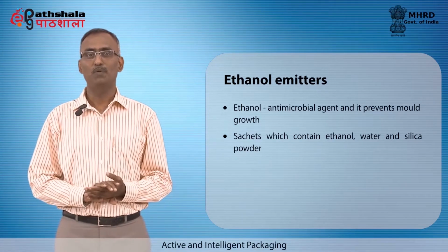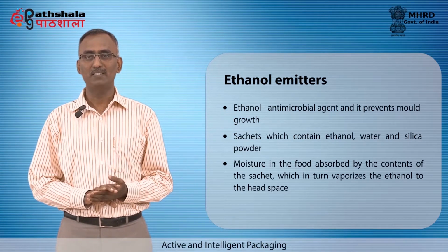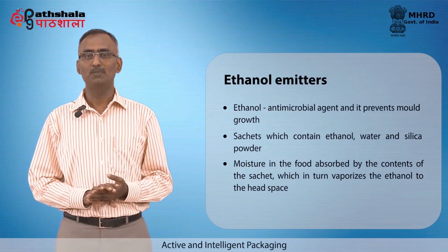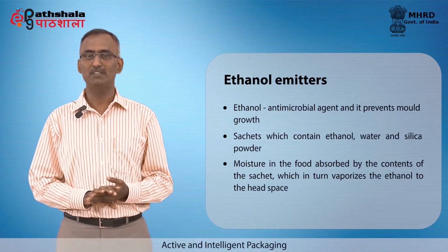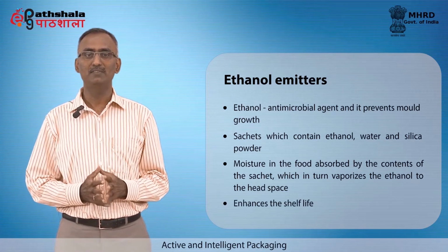The moisture in the food product is absorbed by the contents of the sachet, which in turn vaporizes the ethanol to the headspace. This ethanol is absorbed by the food product, which prevents the mold growth. Use of ethanol emitters enhances the shelf life of high moisture bakery products up to 20 times.